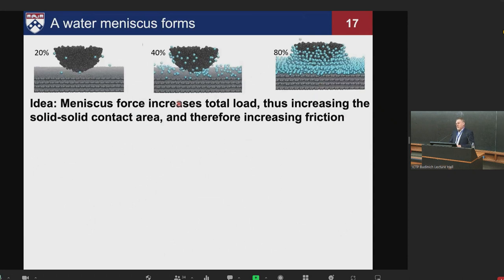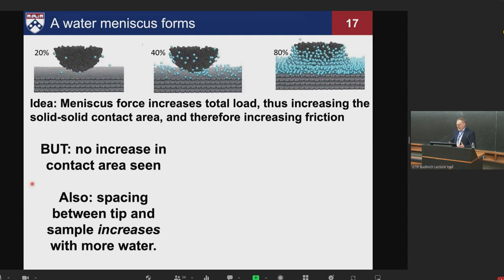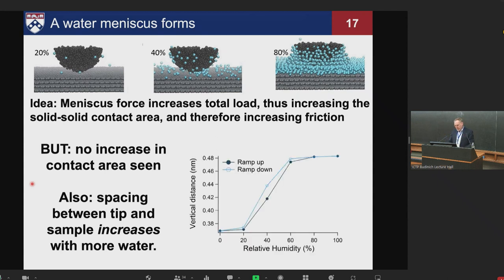So we said, okay, it looks good, but is it really the mechanism or is there anything else going on? Do we really see that the contact area goes up because the capillary forms and causes adhesion? Well, they can get the contact area between the tip and sample. It was not increasing. They saw no significant change in the contact area. And furthermore, if there was adhesion, you would expect there to be elastic deformation as the tip and sample are pulled together by that capillary. And so the vertical distance between a reference point on the tip and sample should decrease. But actually, it increased a tiny amount, only one angstrom net.